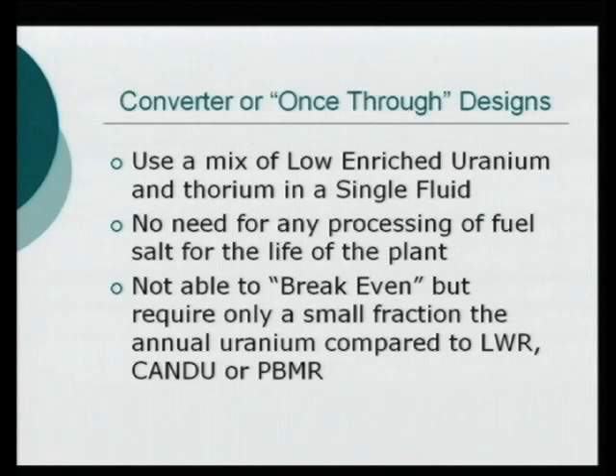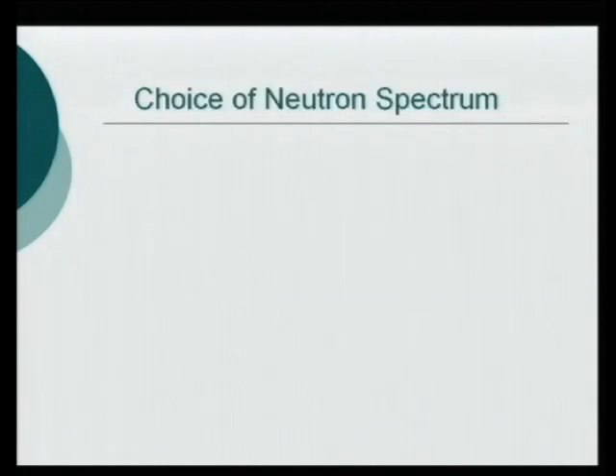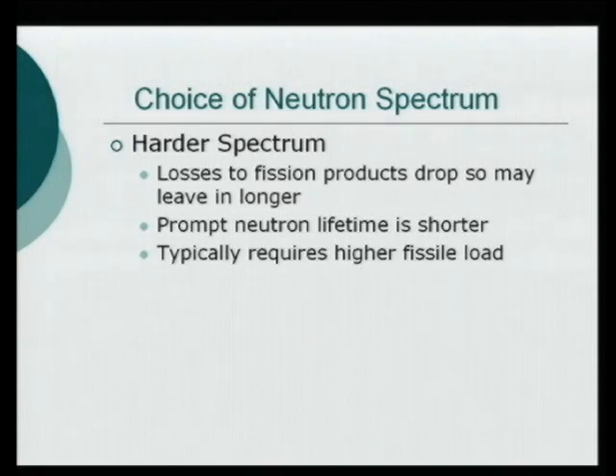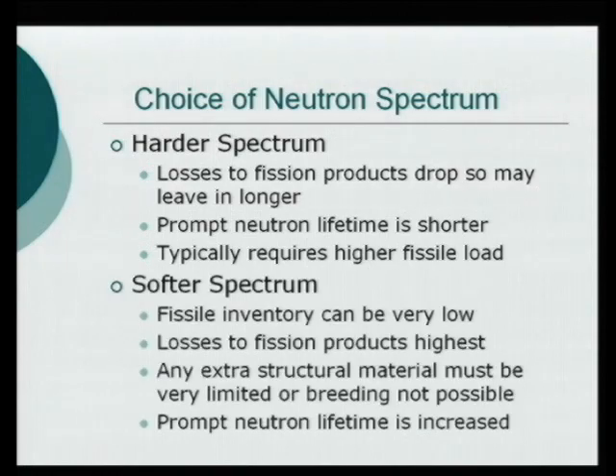Just basically on design basics here, choice of neutron spectrum: a harder, faster spectrum, because we can modify this almost as much as we like. The losses to fission products will drop, so we can maybe leave them in a lot longer. Prompt neutron lifetime is shorter, and that's a bit of an issue on control, etc. And it typically requires a higher fissile load, more fissile material to start these up.